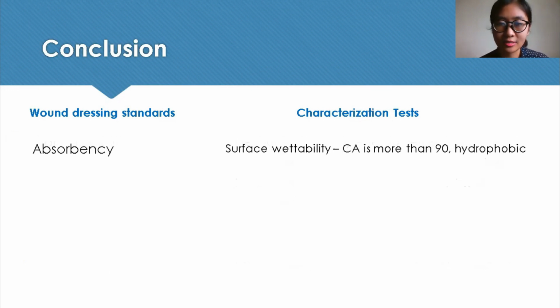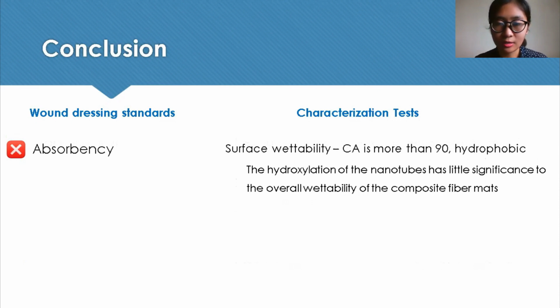As for the material's surface wettability, its contact angle is more than 90 degrees, so the material is hydrophobic, meaning it does not address the absorbency property of a wound dressing. It was also concluded that the hydroxylation of the nanotubes has little significance to the overall wettability of the composite fiber mats. However, the waterproofness property of a dressing can be addressed if the fabricated material is used as an outer layer in contact with the environment, protecting the wound from foreign liquids. So it can be used for waterproofness.